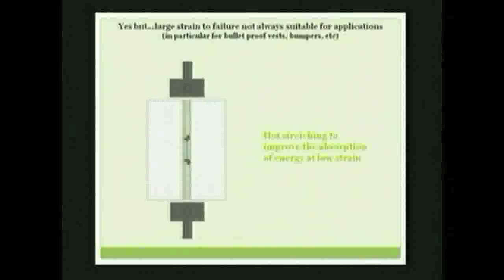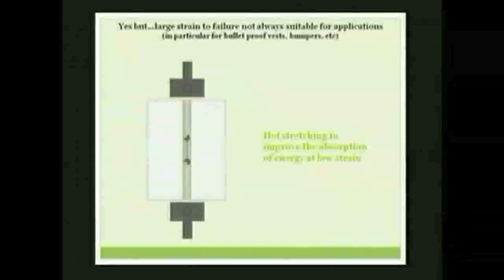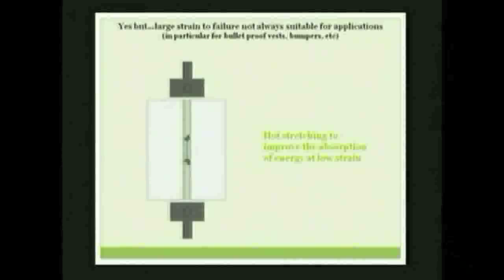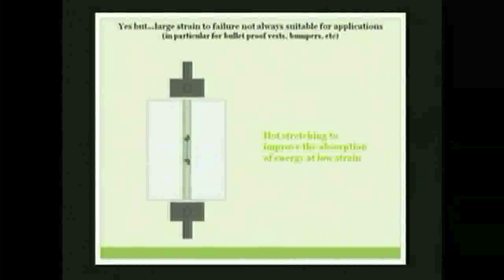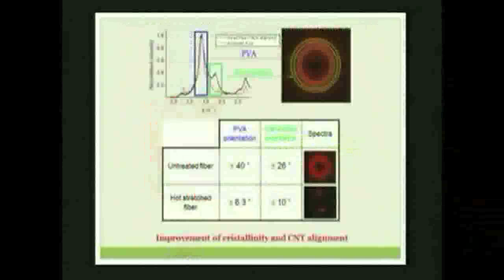What is hot stretching? We put the fiber inside the furnace, and then we stretch it while heating it at the same time. And then we stop heating. And we keep this fiber under stretching, and we cool it down under stretching, keeping the force, keeping the stress on the fiber, okay? And this is something which is widely done in industry, in the textile industry too, to improve the polymer properties. And when we do this, we completely change the structure of the fiber.